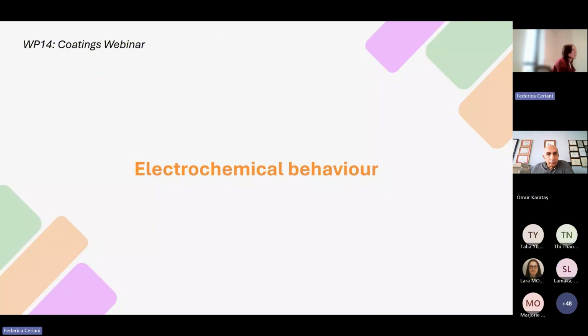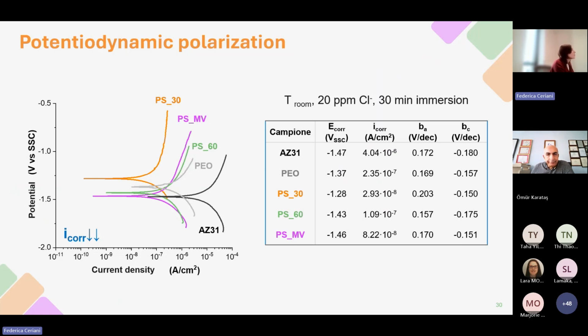Finally, let's briefly comment on the electrochemical behavior of the specimens. The electrochemical characterization is performed through potentiodynamic polarization test carried out in a chloride-containing solution at room temperature. First of all, we could appreciate an increase in the corrosion resistance when comparing the bare magnesium alloy with the PEO-coated substrate. Indeed, the corrosion current density is reduced by 1 order of magnitude. And the protective effect of the PEO coating is further enhanced when sealing post-treatments are carried out. In particular, the best results are provided by the PS30 sample, for which the corrosion current density is reduced by a further order of magnitude with respect to the case of the PEO-coated specimen.